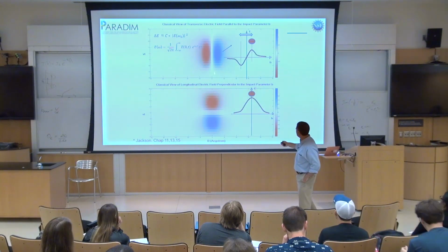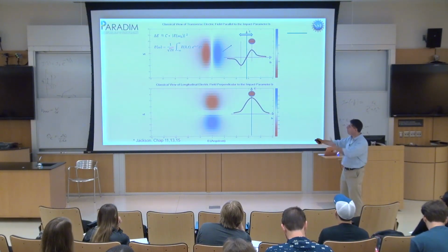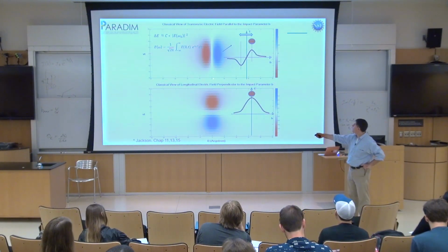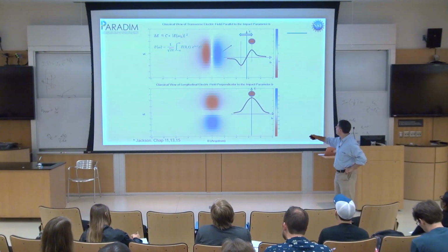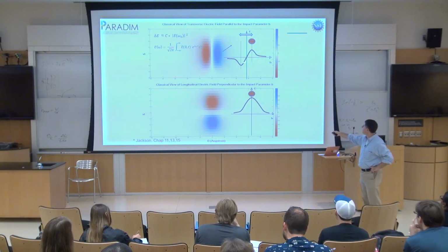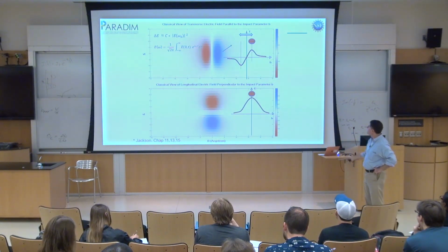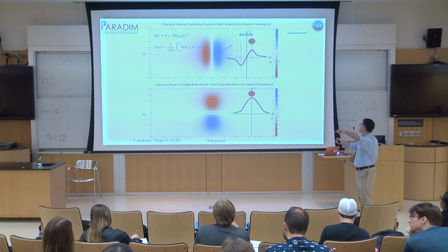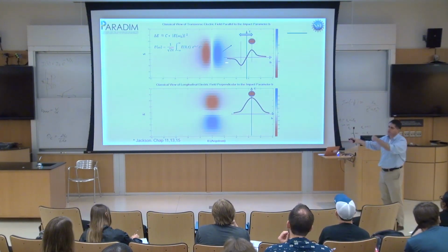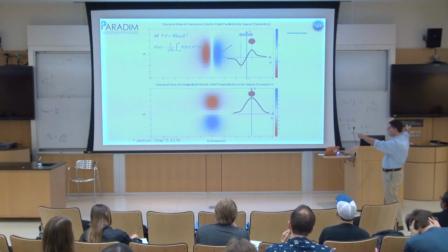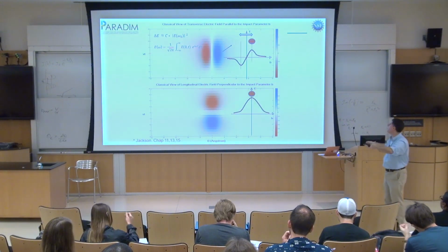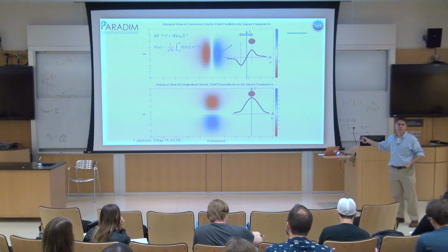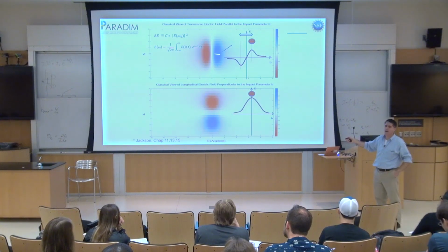So what I've plotted over here is the shape of the pulse as a function of my probe on either side of a little harmonic oscillator atom kind of thing. And you can see that I've pulled the electric field to the left and to the right. If I'm looking at the electric field sideways, over here, the electron in the probe is pushing the electron in the atom away from me. On that side, it's pulling it towards me. So I get a little pulse with an opposite sign on either side.